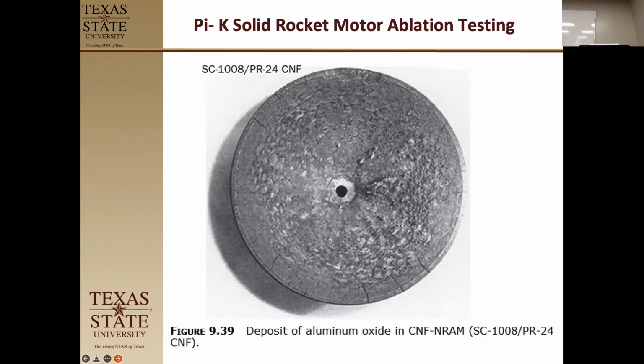It's blowing aluminum oxide out there. It could be in the molten state, could be in the solid state. So what's happening here is the carbon nanofibers are sucking so much heat from the surface. The aluminum oxide is embedding in something. That's the aluminum oxide from the pellet, not the film. So I think what we have here is that, again, heat transfer is being a problem with this. Yeah, and it did crack. So if we use the best insulating material, then I think that is the only contributing factor to this. It's not just that, because you have to have something that's decomposing, off-gassing, pyrolyzing. So it's good to have things that don't off-gas, but you don't want to overload it. You still need those gases to create that foam. That foam insulation layer is very important. So you couldn't just do a solid ceramic or something like that.